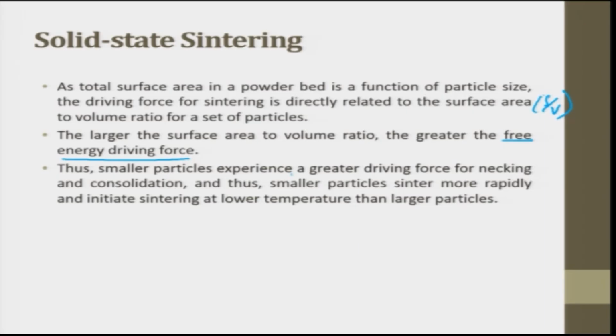Thus, a small particle experiences a greater driving force for necking and consolidation. Thus, smaller particles sinter more rapidly and initiate sintering at lower temperature than larger particles. Very important point: if you can go smaller and smaller in the size of the powder, you will have more driving force, in the sense that you will get better consolidation. And once the particle size is very small, the volume is small and the surface area is large, so the melting point will also reduce.